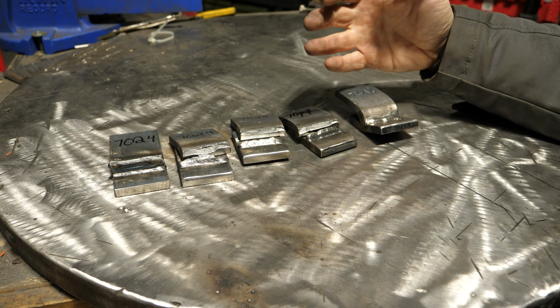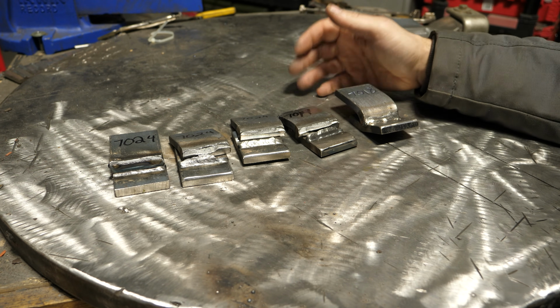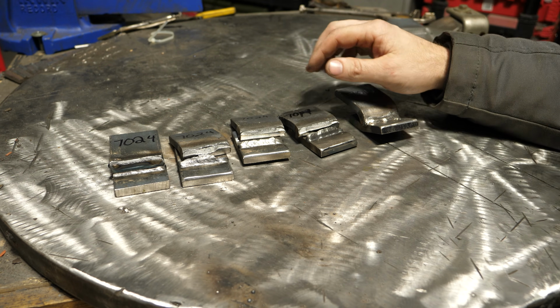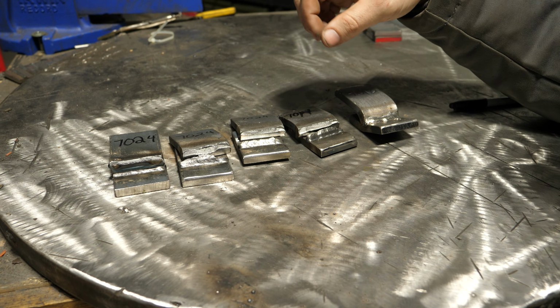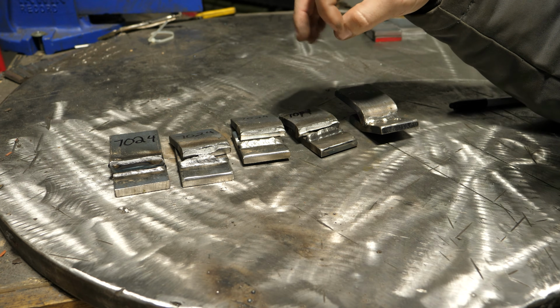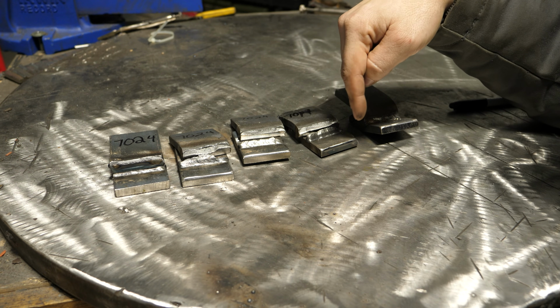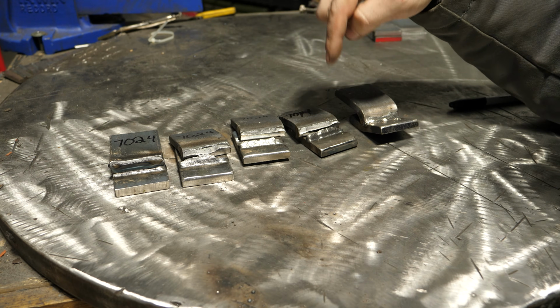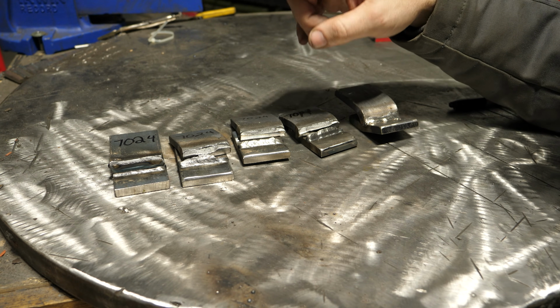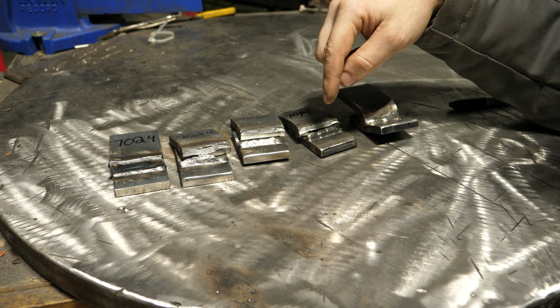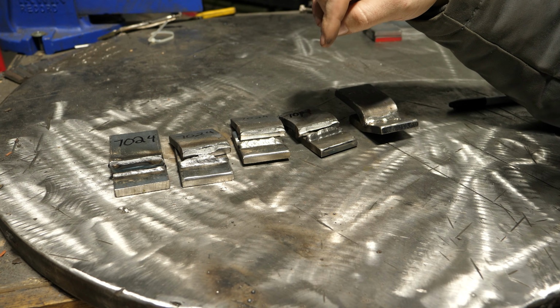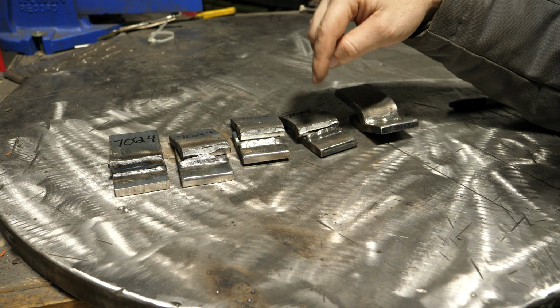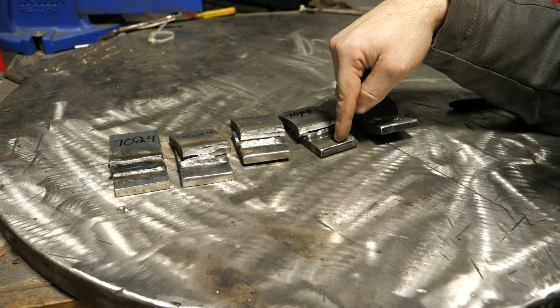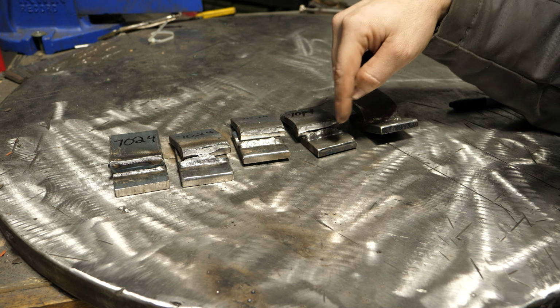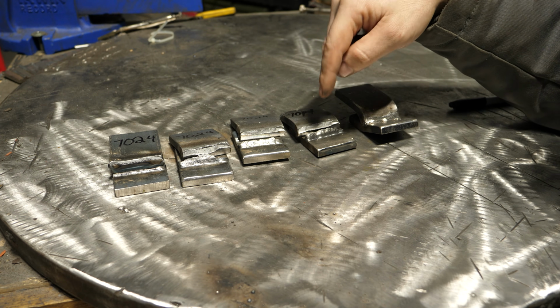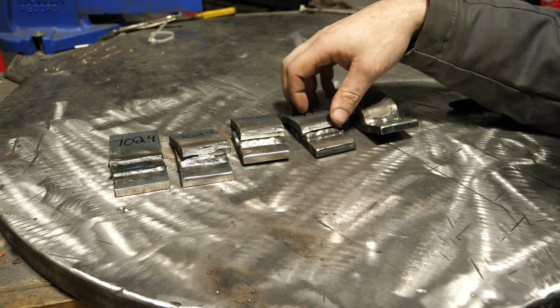There could be, at least in my theory at this point, doing all this testing, two possible reasons for that. One, hydrogen embrittlement. I did a lot of research on this, and A36 hot rolled, which is what this plate is, is not known to be susceptible to hydrogen embrittlement. However, caveat, on thicker plate, half-inch and thicker, hydrogen can play a role in ultimate strength from what I've read. This is close enough, being 3/8, to where the effects that hydrogen may play in this may be enough to cause failure. So that's a possibility.